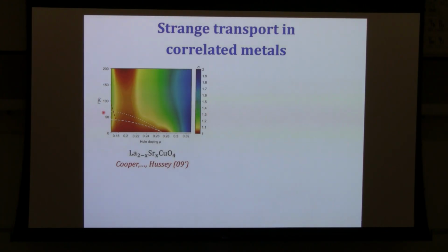So there's a whole phase, apparently, a whole metallic phase, which is characterized by rho being proportional to T. And moreover, this region where the resistivity is linear in temperature seems to terminate not too far from where superconductivity terminates. So these are the two observations. I'll be focusing on this type of regime. In the jargon of the field, this is called a fan, for obvious reasons.